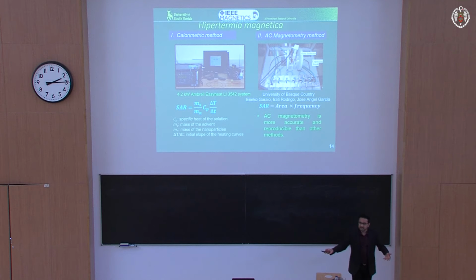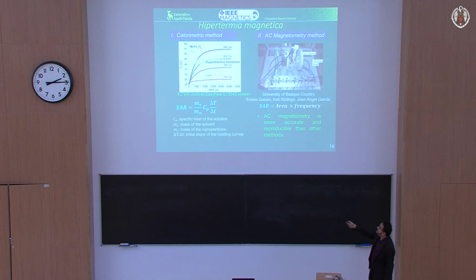So it's a SAR equation. In our case, the data looks like this. This is for manganese ferrite. We take manganese ferrite nanoparticles, and you can see under different conditions of applied AC field at this fixed frequency of 325 kilohertz, we have these curves. And the therapeutic window is 40 to 45 degrees Celsius.